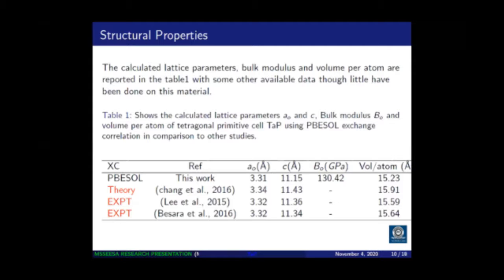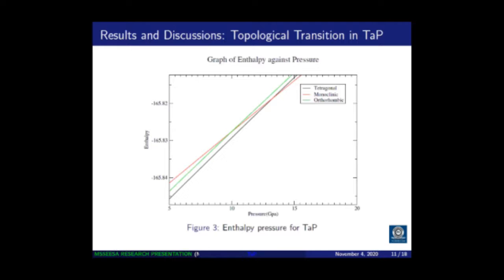I also computed the bulk modulus, and I was able to get 130.42. By the time I was computing this, I didn't get the results for bulk modulus from other studies. And the volume per atom is 15.23, which is also very close to other studies. So as we move to the next, we can see that the results I obtained here are in much agreement with other studies.